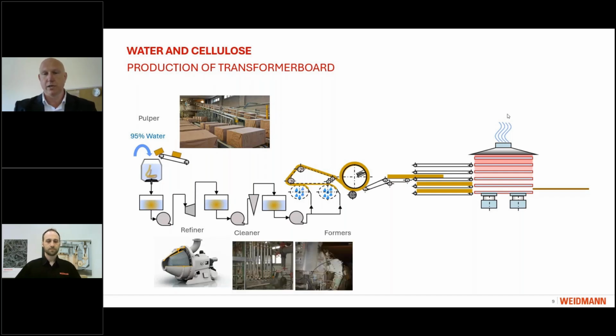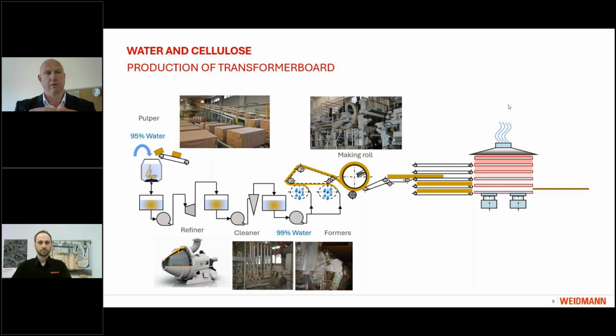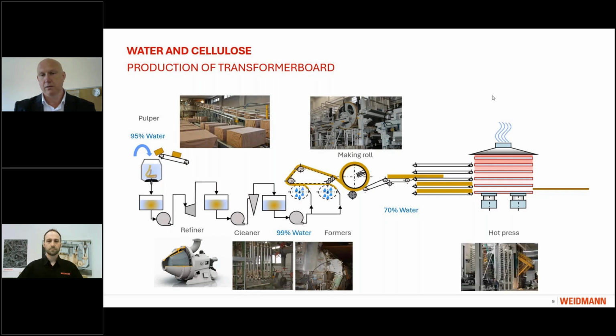During this formation, we already put additional amount of water, and this is already 99% of water and only 1% of fibers. Then we create a fiber mat or wet sheet on the making roll, and this wet sheet already consists of 70% of water and 30% of fibers. Then we have to dry it either in the hot presses or in the drum dryer if we produce the paper. And the final product as a paper or as a board consists of 4 or 5% of water, and the rest, this is the fibers, 95% of fibers.